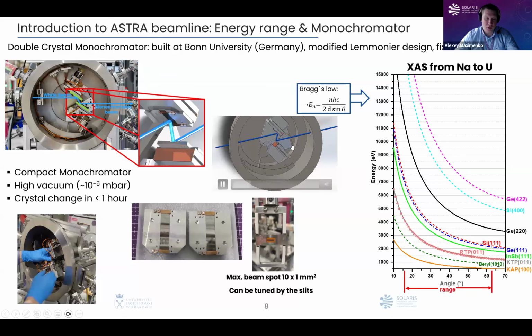What is also very important is that in this construction of the monochromator, we don't have step motors inside which govern the movement of the crystals. We have only one stepper motor which governs the movement of the first crystal, and the second crystal is connected mechanically to the movement of the first crystal. When the first crystal is moving, the second crystal makes a quite complicated movement via a mechanical chain. This type of solution allows us to measure at such low angles and achieve such low energies.